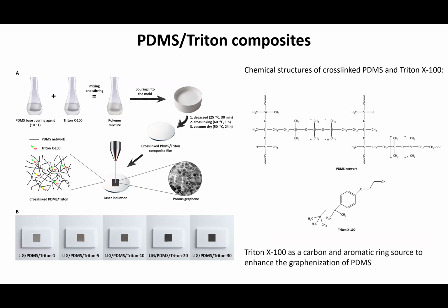One of the first things we did also was PDMS-based polymers. PDMS is a very common polymer that is used in wearable devices because it's biocompatible, it's soft, stretchable, etc. But by itself, although it contains carbon, it doesn't seem to have enough carbon to make high-quality graphene from it. The structure of PDMS is shown here, this large PDMS network. So one of the things we did was to add Triton to it. Triton is a compound that contains aromatic rings that act as carbon sources to enhance the graphenization of PDMS.